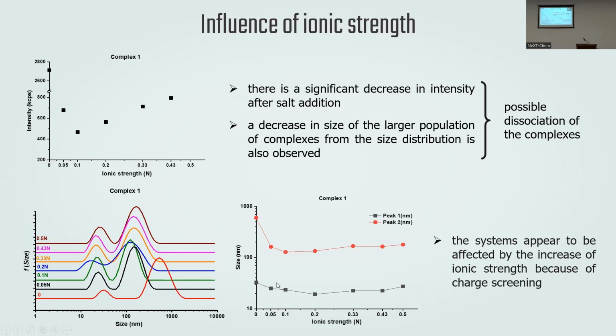Also, we can see from the third figure that the size of the first population isn't affected, only the size of the largest population, which decreases. These results suggest that the systems appear to be affected by the increase of ionic strength because of the charge screening effect.